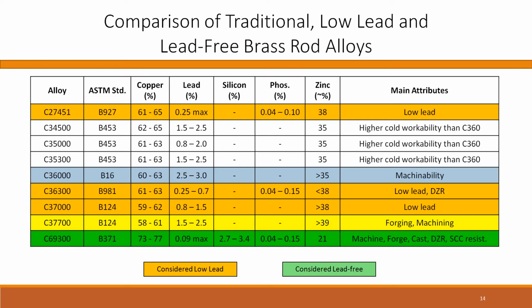The other fairly popular alloy, in terms of volume for rod, is 377, which is the bright yellow row, and that's got about 58 to 59% copper, 2% lead, and around 39% zinc, and that one's very good for forging, and it's not a bad machining alloy.